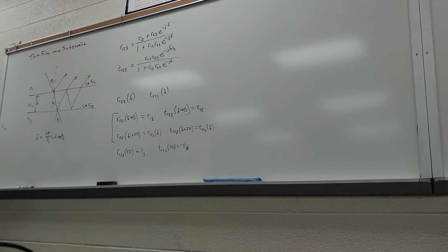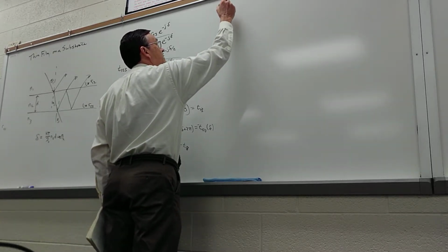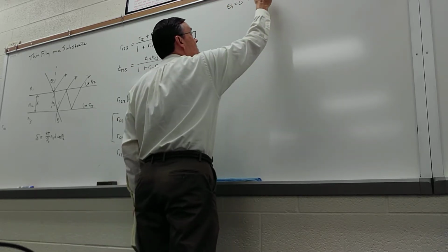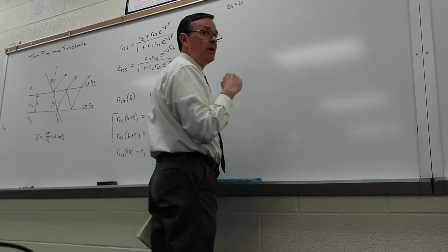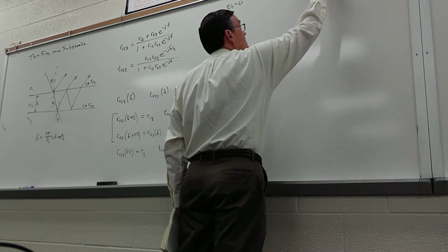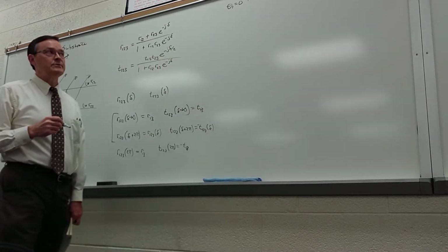Well, maybe this material is sensitive to something in the atmosphere, and so you put encapsulation on it to protect it, but you don't want this to disturb the optical properties. Well, you can do it. It's not a problem. If we look here, for the case of, let's say we have normal incidence, so theta 1 is 0 degrees, and we look at the case of delta equal 2 pi, then we can solve for the thickness, and the thickness will be equal to lambda naught over 2 N2. So I'll let you do the algebra.